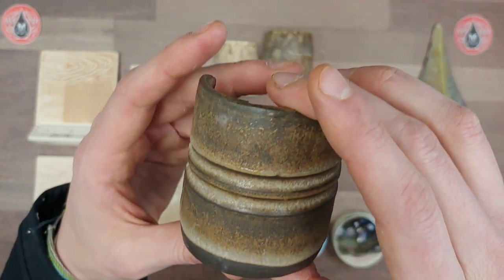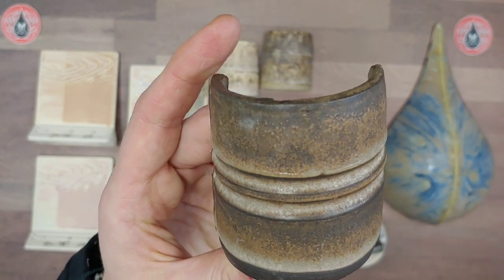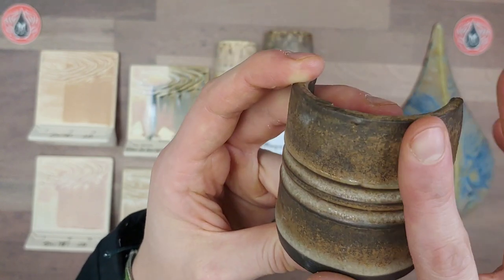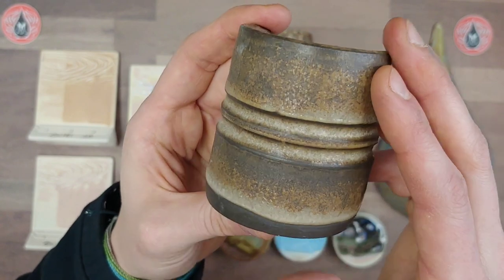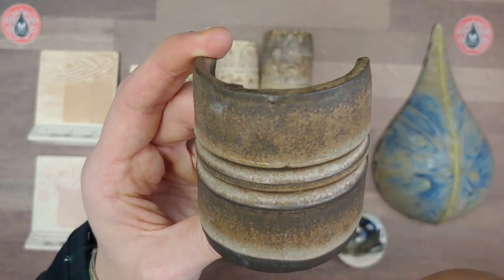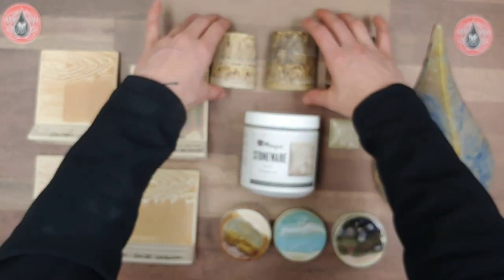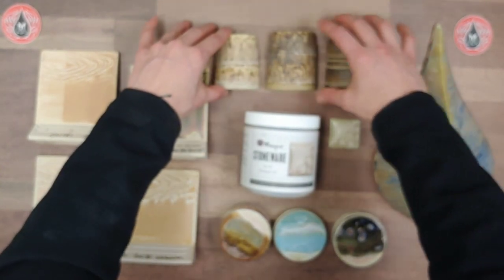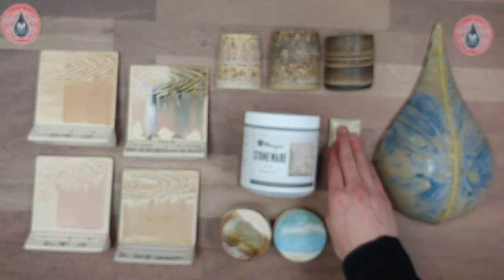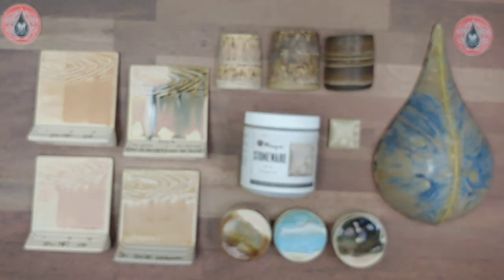Here we have it on the dark brown clay — this one shows up a little better than the other four in this line. We have a little more color contrast and a nice smooth finish. This is fired to cone 6 with a slow cool to prevent pinholes. For alternative clay bodies, the slow cool seemed to work better than a hold, even though we typically recommend a hold when moving away from the white stoneware.